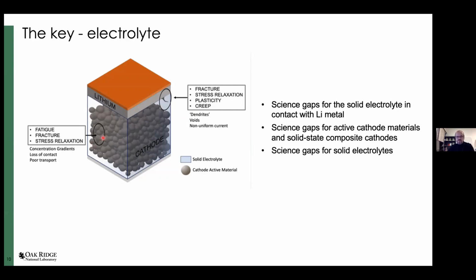And when it comes to the interface with the cathode, simply because repeated insertion and removal of lithium ions creates strains, we're well aware of that, especially in the layered transition metal oxide materials. You have strains along the z-axis, so your electrolyte should maintain contact with those particles throughout the cycle. That's the idea.